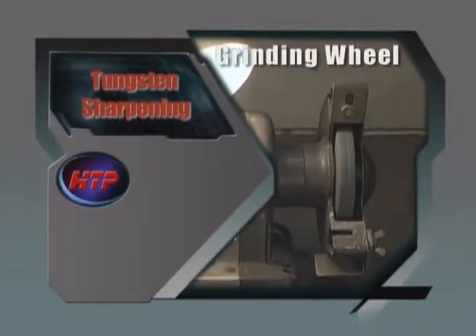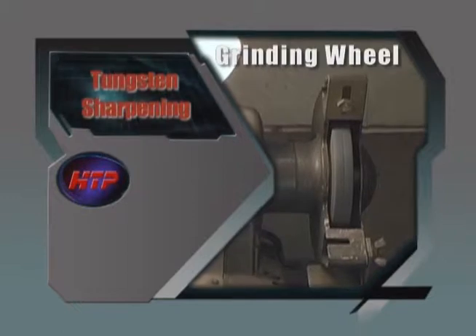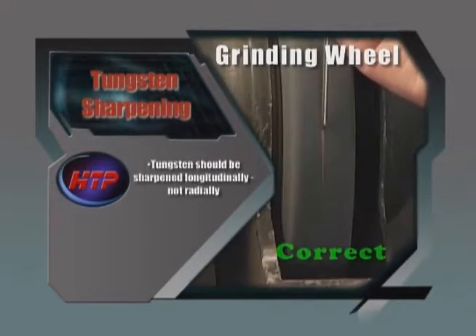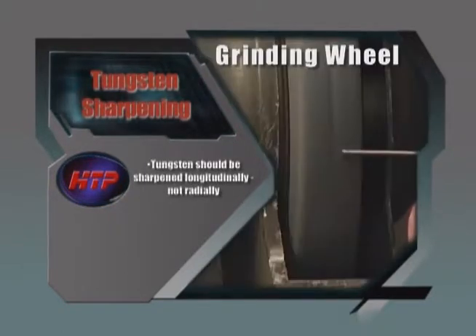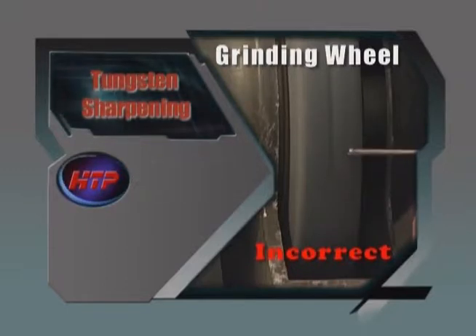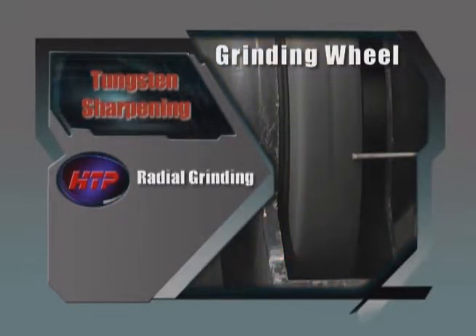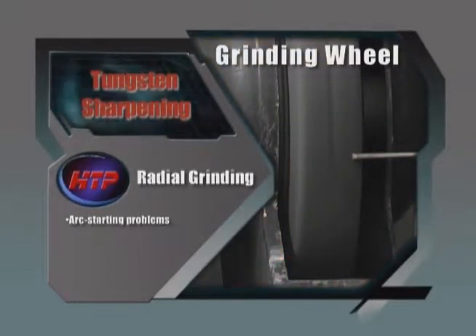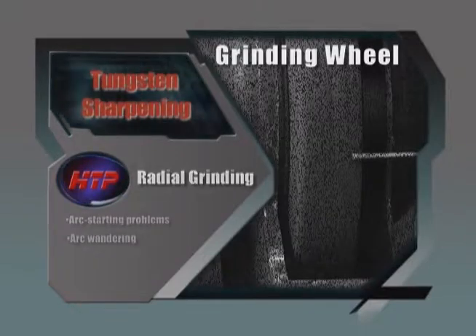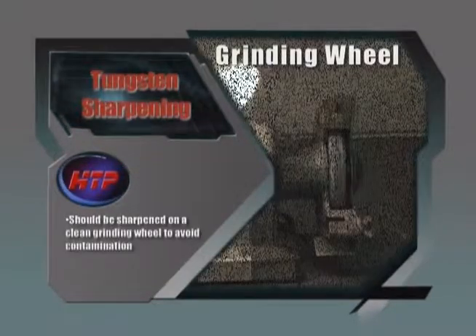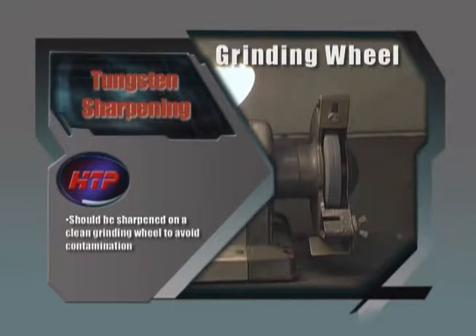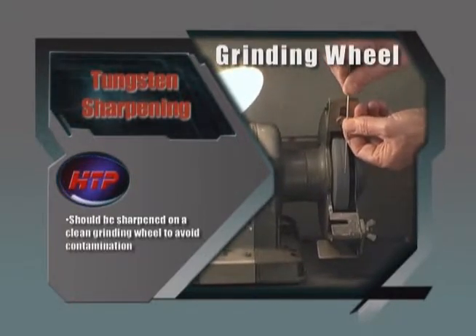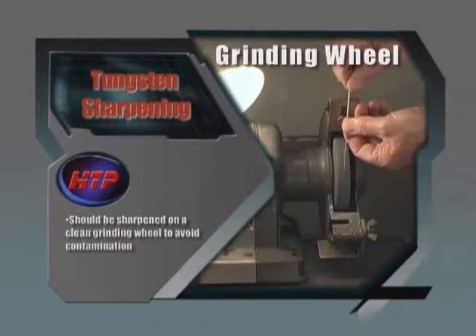Tungsten should always be sharpened so the grinding marks run along the length of the tungsten, or longitudinally, never radially. Radial grinding marks will cause arc starting problems and arc wandering. It is also important that the tungsten be sharpened on a clean grinding wheel that will not contaminate the tungsten. Preferably, this grinding wheel will only be used for sharpening tungsten.